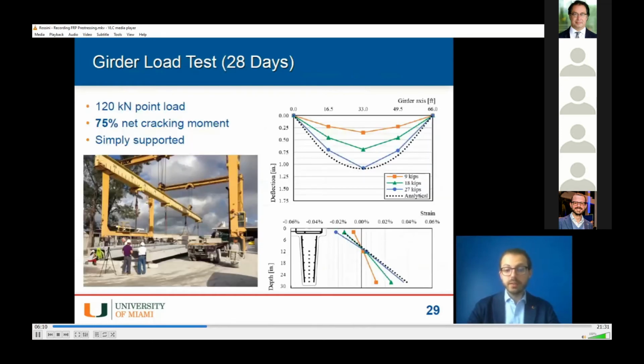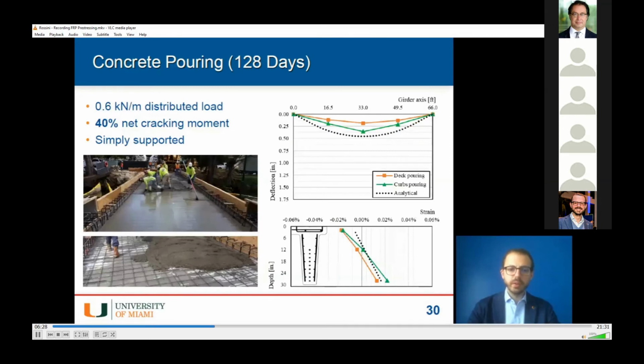And then load testing. The first one was performed at the precast site. One of the two double T girders was loaded with a crane up to 75% of its net cracking moment. And here you can see quite a good agreement between our theoretical expectation and the actual behavior that we recorded on site. We were also able to monitor the performance of the girders during concrete pouring because we knew the weight of concrete and we had the structure instrumented. And also in this case, you see quite a good agreement with our expectation.